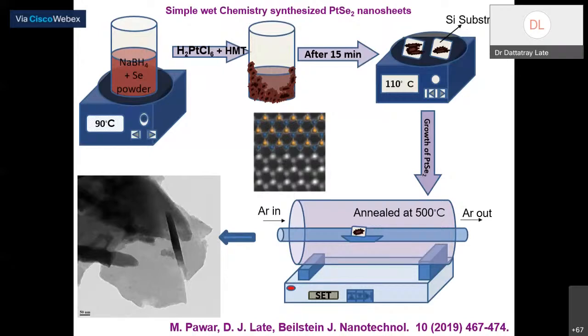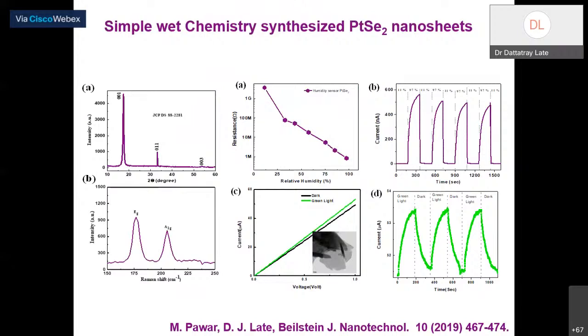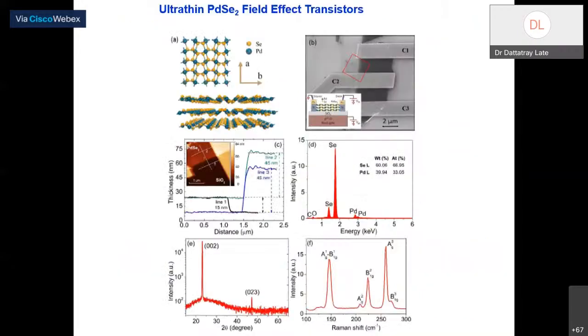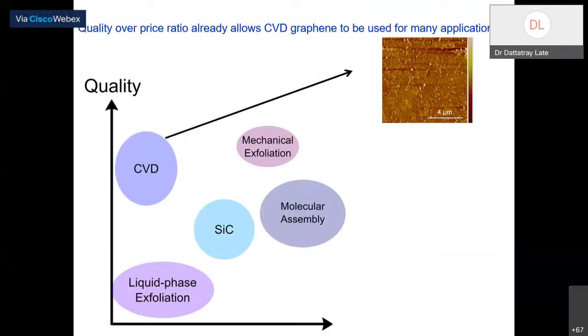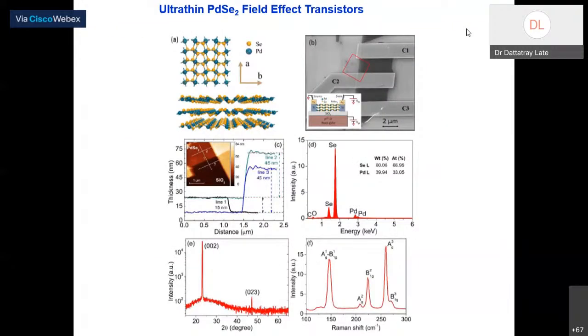We found that the material synthesized is PtSe2, and then, of course, characterized it using various methods like XRD, Raman spectroscopy, TEM, and all these things, and found that this material can be used for gas sensing applications, for example humidity sensing, photodetector applications, and all these things. Another material is PdSe2. Again, we have a transistor-based sensor application. The material is synthesized and characterized using XRD, Raman, TEM, and all these things, and we find that this material also has very good applications, right?